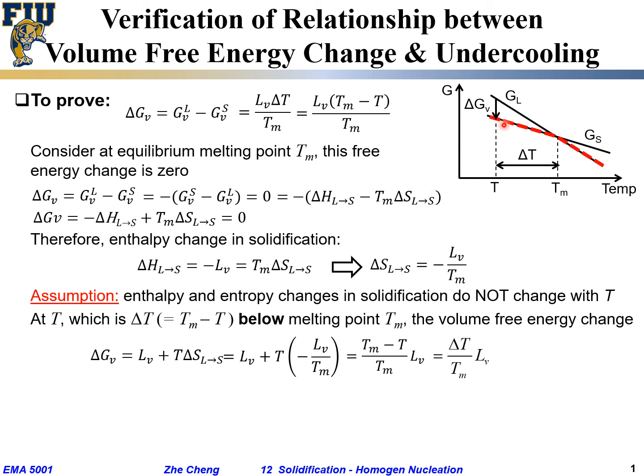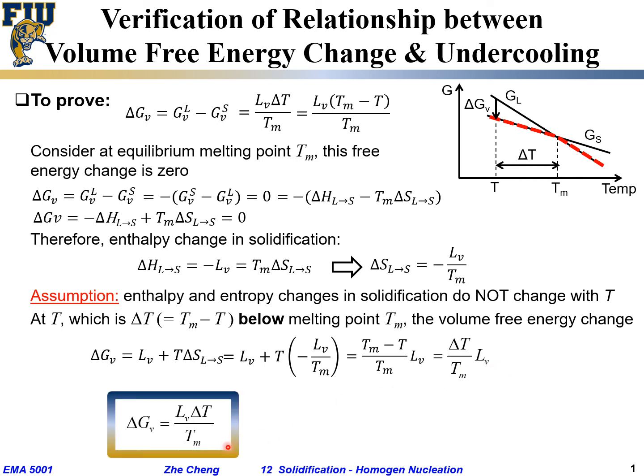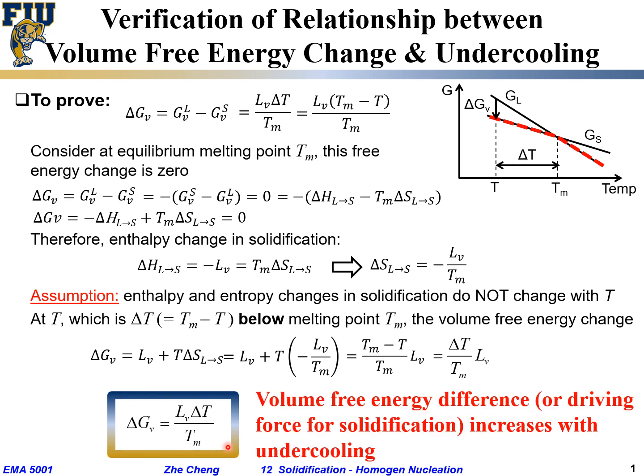This is how we prove that the volume free energy drop per volume from liquid to solid is a linear function of ΔT, the under cooling. For a given system, both Tm and the latent heat Lv are fixed. So the positive driving force for solidification — the volume free energy difference from liquid to solid — increases linearly with under cooling.